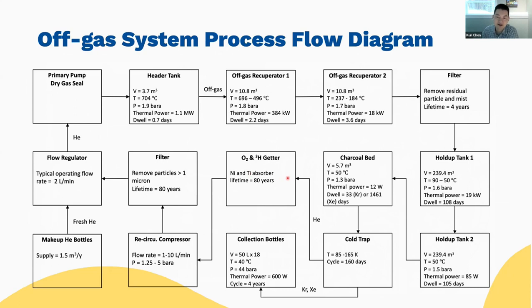So this getter will be more than adequate to absorb the residual tritium from the system. And after this, the off gas has pretty much been cleaned up. It will go to the recirculation compressor, and then it goes to the filter. Again, this filter has the capability of removing particles that are larger than 1 micron. So after this, it will go to the flow regulator. It controls the flow of the whole system, and then it is pushed back to the pump and goes through the dry gas seal and back to the header tank.